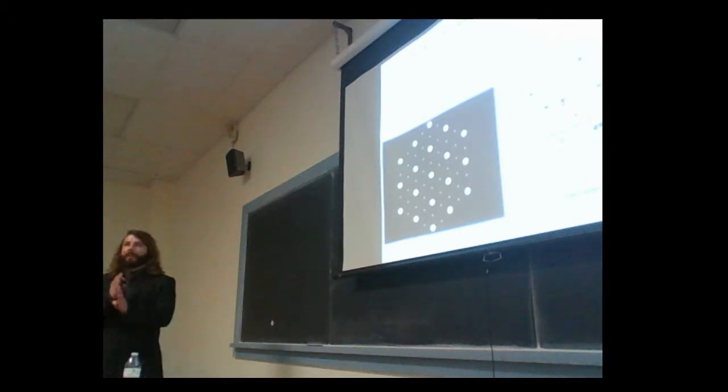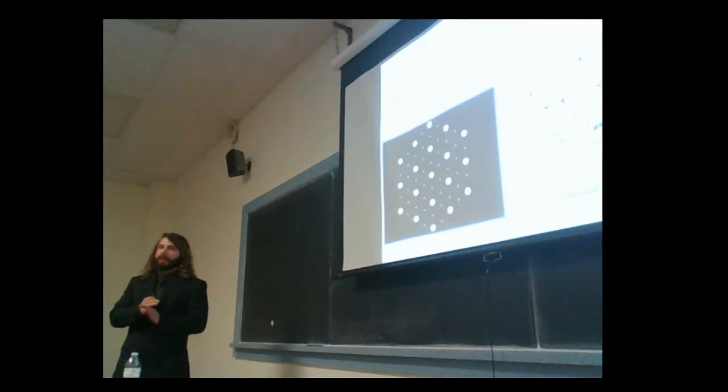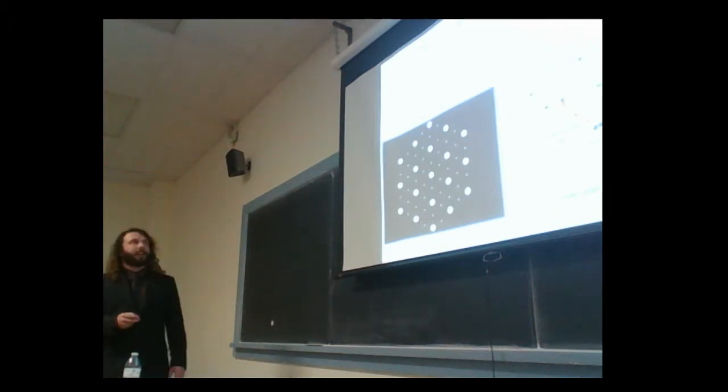The normal lattice is an integer multiple of the superlattice, and so these systems are highly coupled. But as you dope the material with copper, the superlattice peak broadens and it starts to become misaligned with the normal lattice peak. As you continue to dope it with copper, this misalignment, called incommensuration, becomes larger and larger.